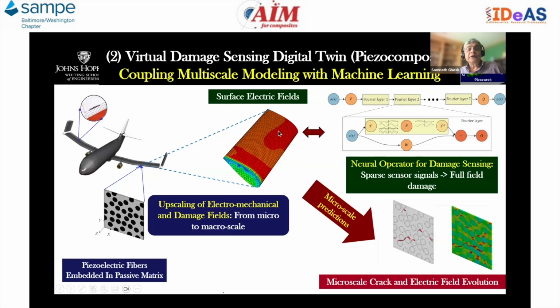Now, in order to get a fast full field prediction, a full field reconstruction of these coupled electromechanical damage fields, it's a good idea to incorporate machine learning, because machine learning has various good attributes for developing fast, efficient surrogate models. We can use certain machine learning techniques, and I'm going to go into that in detail. Here I'm showing a neural operator for damage sensing that can clearly show the full field development, and from there we can zoom in locally to see the evolution of the microstructural state variables, for example the deformation, the fracture, as well as the electrical fields.